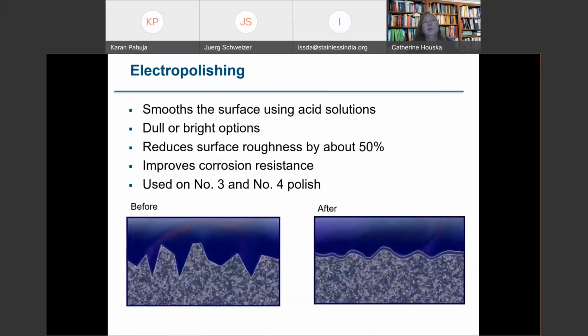Electropolishing smooths the surface. It's an acid treatment. It generally reduces the surface roughness by about half, but that can vary. And it's often used on a surface that has been mechanically polished by a number 3 or number 4 polish to smooth it, when otherwise handwork would be needed, or it's a surface that is challenging to polish. Door handles and artwork and a variety of other surfaces are often electropolished to smooth them.